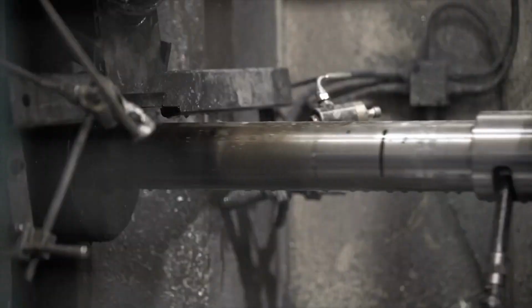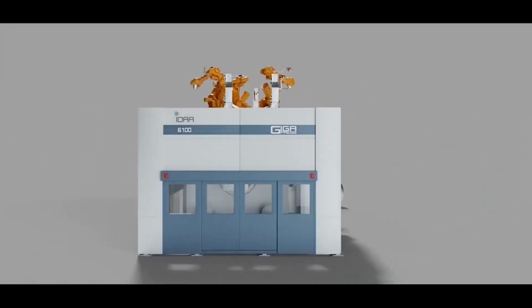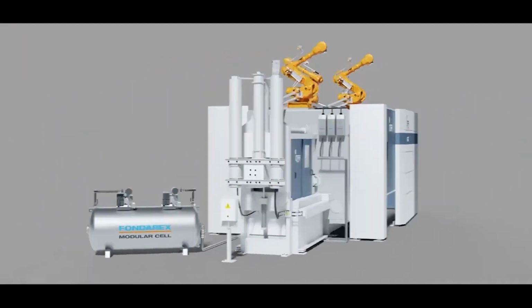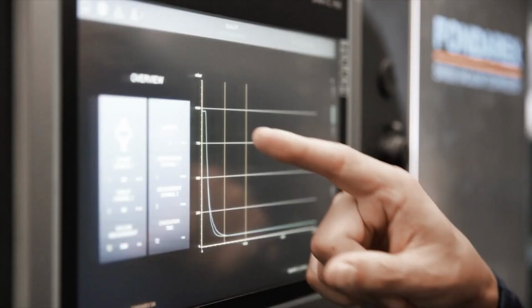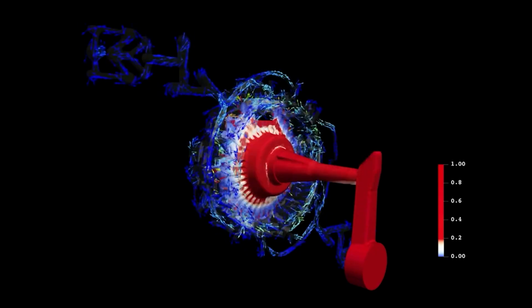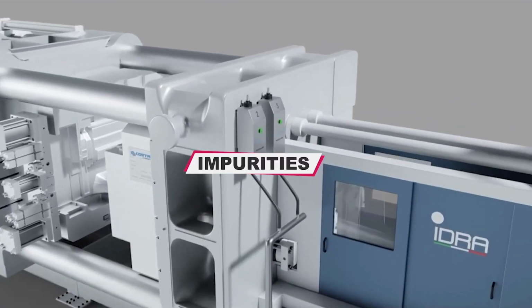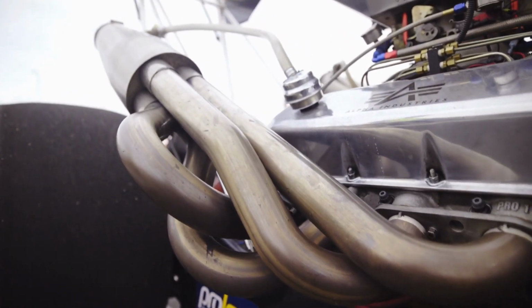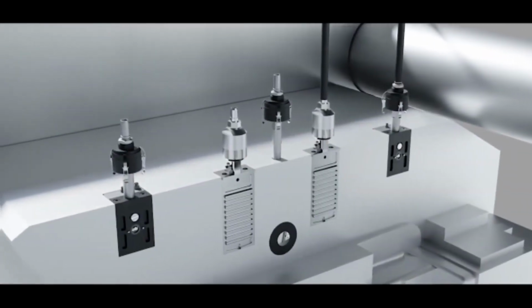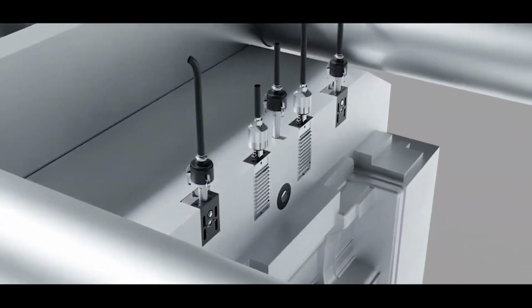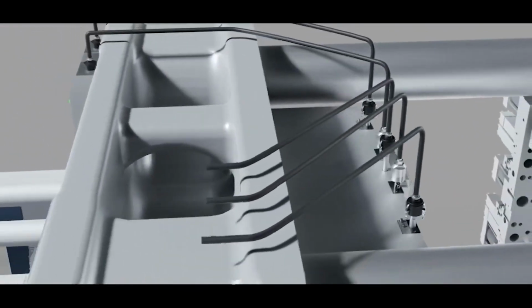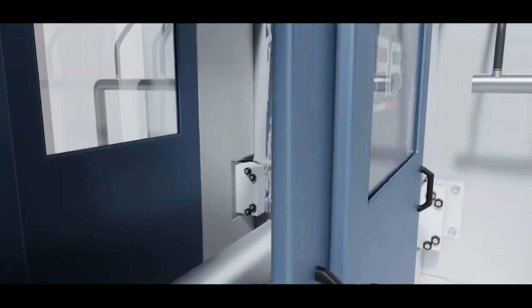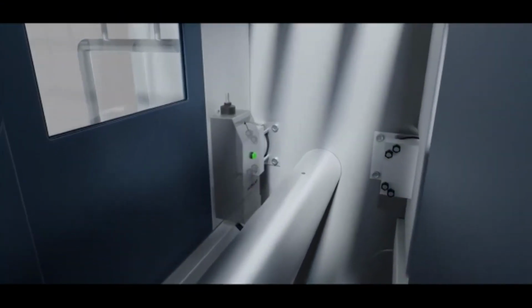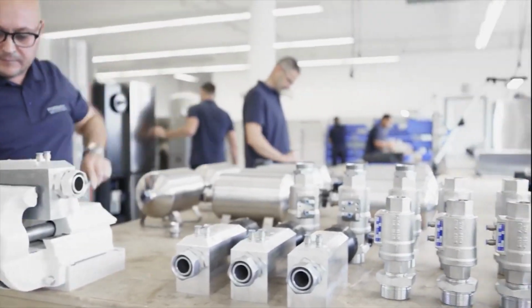So how does this massive device function? The functioning of the Gigapress can be divided into the following steps. The preceding casting cycle's aluminum ingots and cutoffs must first be melted at 850 degrees Celsius in an oven. After purifying any impurities using hot pipes, the liquid metal is moved into another enclosed oven. Between 750 and 850 degrees Celsius is the temperature maintained in that oven. The growth of oxides in the molten aluminum is halted by introducing nitrogen gas into the storage oven. It also helps maintain a steady temperature.